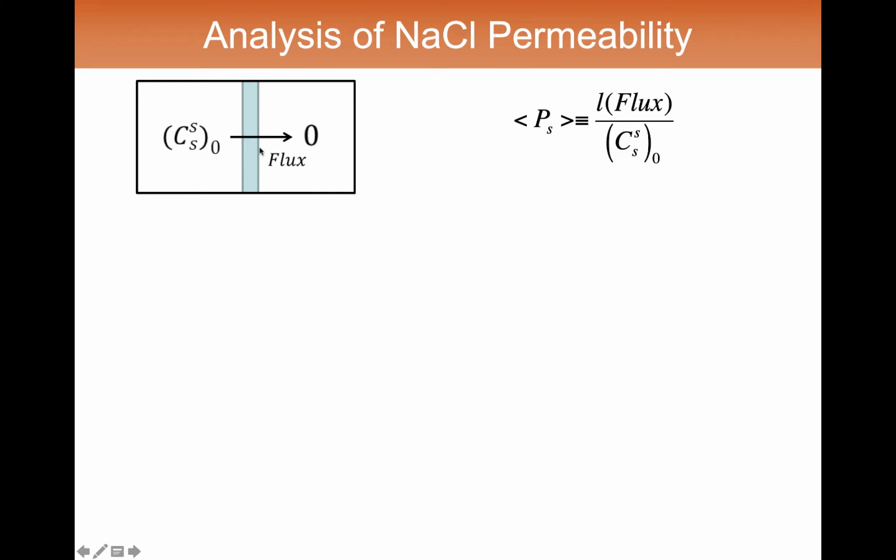across that entire membrane. It turns out that to compare with the ionic conductivity measurements, where the salt concentration is going to be the same on both sides of the membrane, but we're going to apply an electric field, we need to know the salt permeability at a particular, precise concentration of salt and not just the average salt permeability. Now, the tools to convert these average permeabilities to so-called local permeability coefficients, or permeability coefficients that would be accurate at a specific concentration, are well known in the literature.